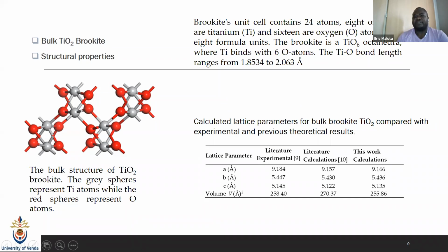And then what we have here, we are showing the calculated properties of the bulk TiO2 Brookite, where we normally use the literature to look at our current calculated values, whether the experimental literature and the other theoretical calculations and what we get are in line with each other. And then we can continue to look at the other properties after making sure that our bulk properties after the relaxation of the materials are in line with the other experimental or literature values.